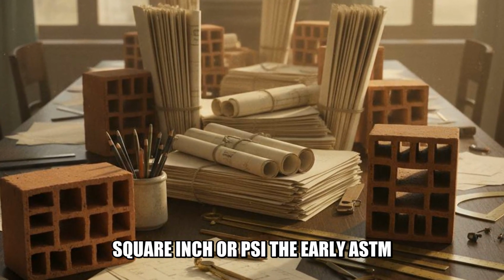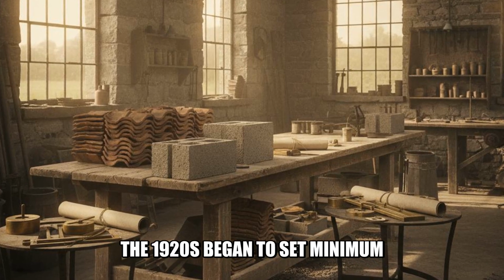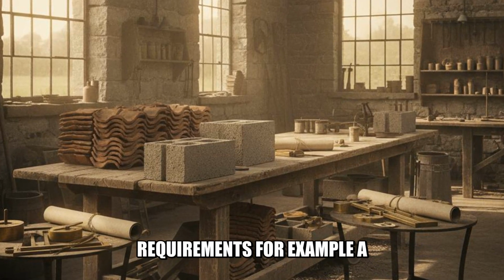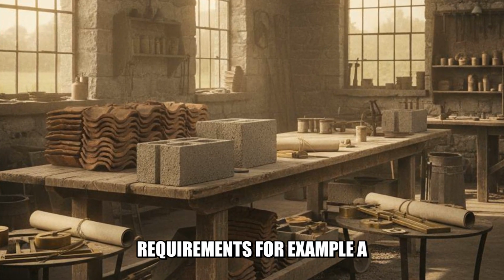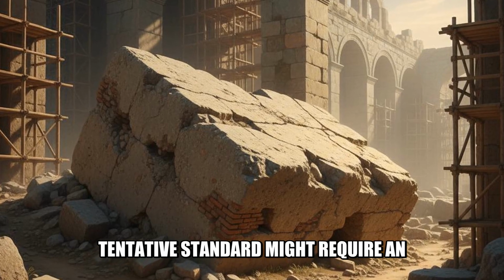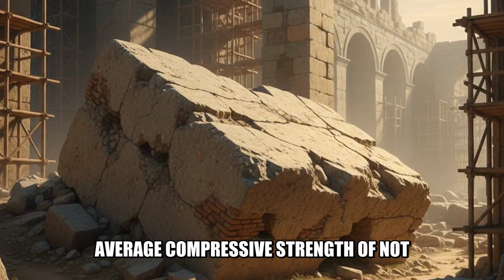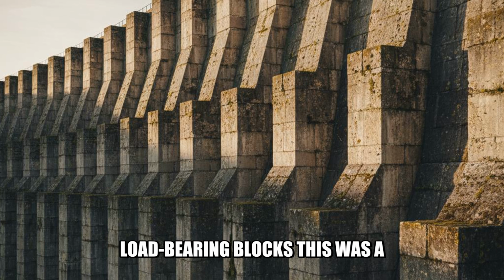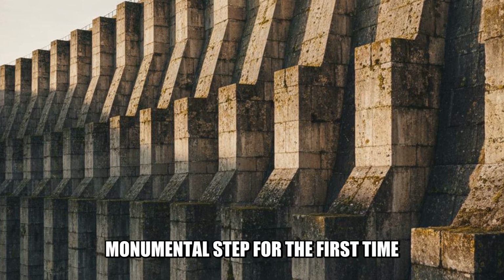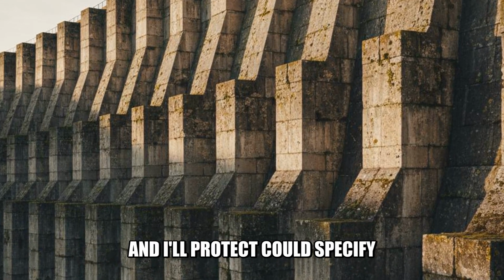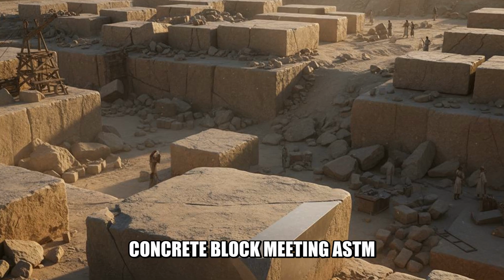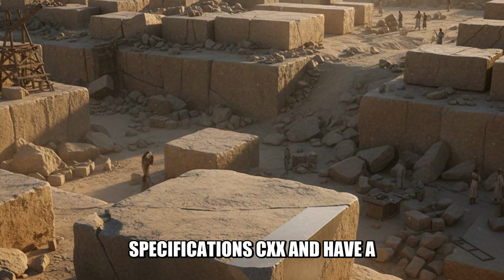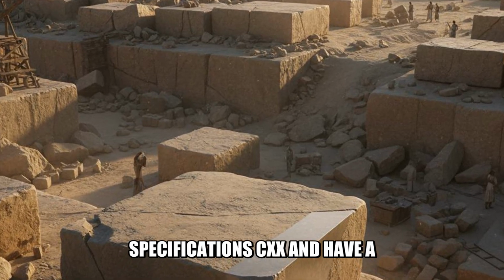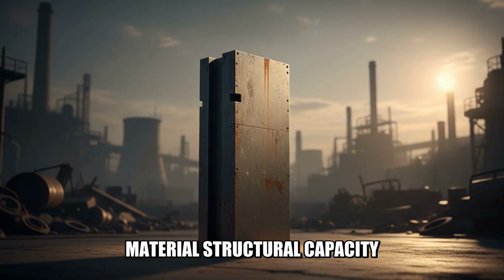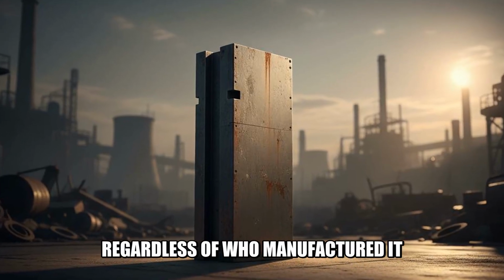The early ASTM specifications, developed through the 1920s, began to set minimum requirements. For example, a tentative standard might require an average compressive strength of not less than 700 psi for load-bearing blocks. This was a monumental step. For the first time, an architect could specify concrete block meeting ASTM specification CXX and have a reasonable assurance of the material's structural capacity, regardless of who manufactured it.